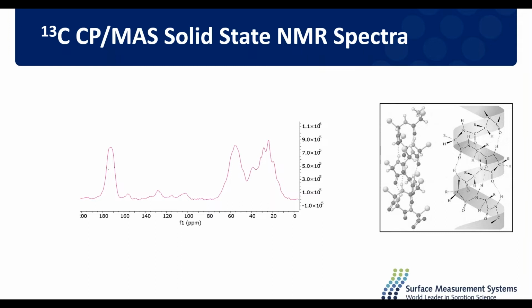The cross-polarization aspect is simply using the natural abundance of the protons in our sample to increase the intensity of these carbon peaks, which have a low natural abundance. And so we get our carbon-13 spectrum. We have our aliphatic carbon peaks from the amino acids, a couple of peaks in that broad area at around 20 to 30 ppm. We then have our alpha carbon peaks from the amino acids, forming this rather broad peak at around 60 ppm. We then have aromatic peaks from the aromatic amino acids, such as phenylalanine or tyrosine. And then finally, we have a peak which is representative of all the carbonyl groups in the keratin structure.